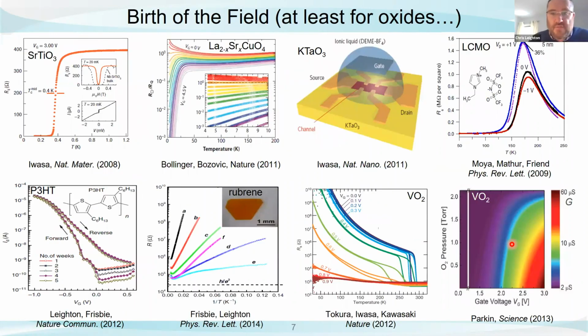It turns out these things are really powerful. So actually, this is a topic with a very long, very interesting history, but it really got going, at least in magnetism and in the field of oxides and superconductivity, about 2008. Iwasa's group really deserve an enormous amount of credit for this. They took a strontium titanate insulating wafer. They put an electrolyte of the type I showed you, or similar to it on the previous slide. They applied 3 volts, and they generated enough electrons on the surface of the strontium titanate to make it metallic, and even it went superconducting.